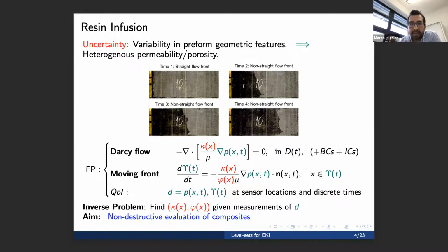And in some extreme cases, the resin will not fill some areas due to the very low values of porosity and permeability, and then it can create a defect. It creates a bubble, and that's a defective part. In some cases, it could be very high, and then the resin will run across this area and will not fill. It will end the process before it completely fills the reinforcement.